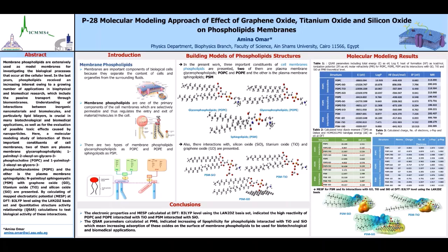There are two types of membrane phospholipids, glycerophospholipids and sphingolipids. In this work, phosphatidylcholine POPC and phosphatidylethanolamine as types of glycerophospholipids, and sphingomyelin PSM as a type of sphingolipids. The molecular interaction of these phospholipids and their interaction with the nanomaterials graphene oxide, titanium dioxide, and silicon oxide through oxygen of the phosphate group of the phospholipids are calculated using density functional theory.